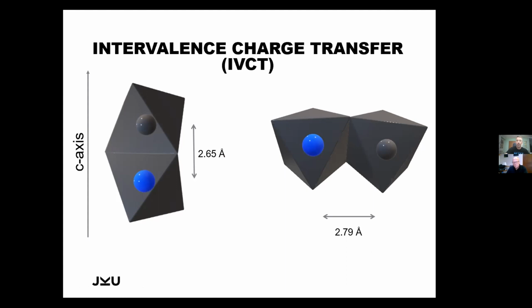Angstrom is a measure that we use in chemistry, because a lot of bondings, atom sizes and ion sizes are in the range of angstroms, and it's easier to explain everything instead of having nanometers, micrometers, and whatever. The second case that we have to look at is if two of these octahedrons are connected via one edge. In this case, we also have the neighboring iron and titanium, but the distance is a little bit further away. They are 2.79 angstroms apart. Not that much of a difference, but a big difference in energy. In the first case, where they're closer together, the orbitals overlap more than here. And if the orbitals overlap more, then it's easier for one electron to jump from here to here than when the orbitals are not overlapping that much. Therefore, this charge transfer is easier and more prominent than this one.